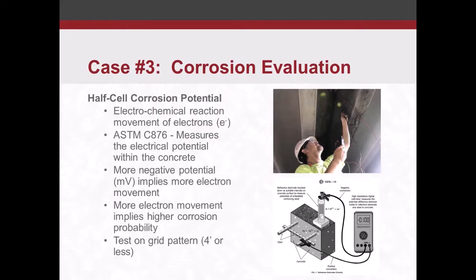Corrosion's an electrochemical reaction, and it involves a movement of electrons. Half cell corrosion potential, ASTM C876, measures the electrical potential within the concrete, and we're measuring in millivolts. The more negative that voltage potential is, it implies that there's more electron movement. Remember, electrons are negatively charged, so we get that negative voltage. The more electrons that are moving around, the theory is that there's more corrosion taking place at that particular location, between the cathodes and anodes, with the electrons moving around. So that's why we get the negative voltage.